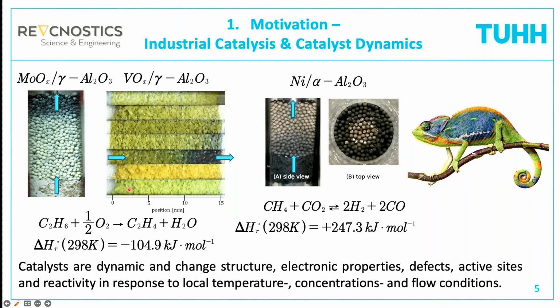So what you can take from these pictures is that catalysts are dynamic and change structure, electronic properties like the oxidation state, defects, the active sites, in response to local temperature, concentration, and flow conditions. So you can imagine the catalyst is some kind of chameleon. I put here this cute chameleon because the chameleon also changes its color depending on the habitat where it lives. But there is one distinct difference between a chameleon and a catalyst. The chameleon will, even though it changes color, still behave as a chameleon. It will walk slowly and it will catch insects with a long sticky tongue. So it doesn't change its reactivity, but the catalyst also changes reactivity if it changes the structure. And this creates a nonlinear feedback loop and makes it very difficult to predict the outcome of such a reactor, end of pipe, based on these very simplified kinetic models that I showed you initially.